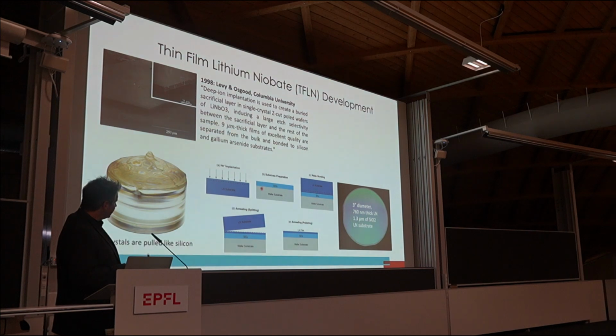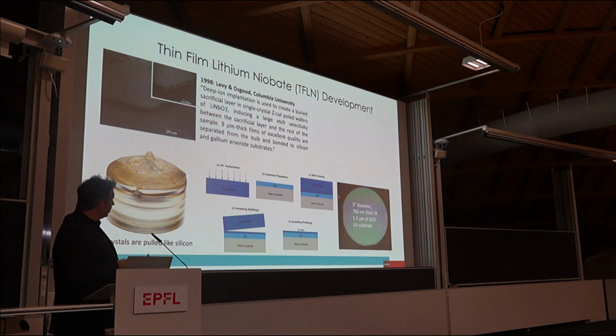Then you prepare another substrate with silicon oxide and silicon, and you bond this lithium niobate wafer on top of it. You thermally stress this layer so that the structure breaks at this damaged region, and then you polish it to make it nice and smooth and flat, and that's it. This is called the smart cut ion slicing process. The same process is used to make silicon on insulator and many other platforms.